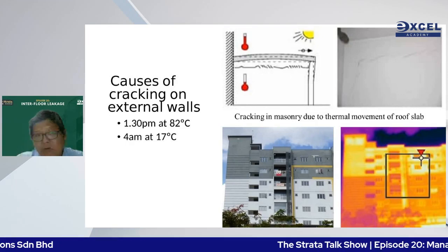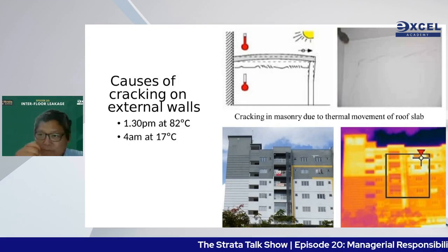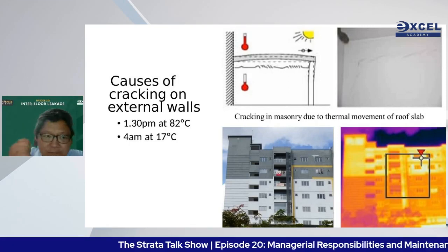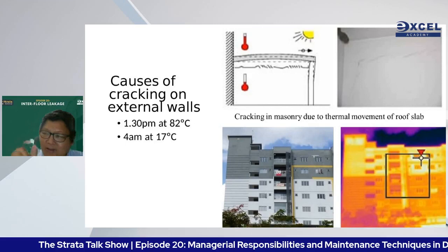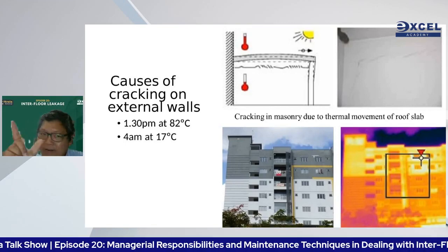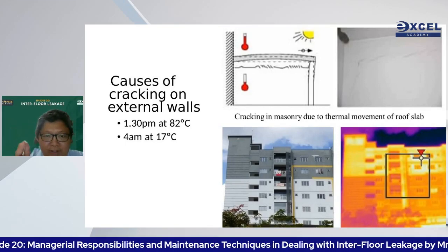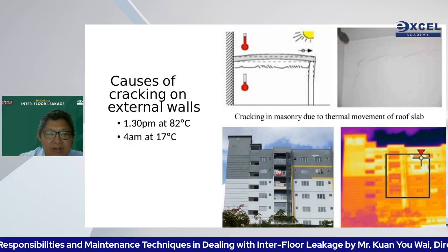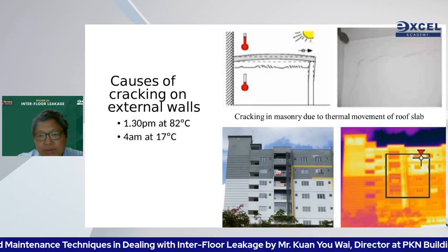And do not try to fill it up with cement, because once you block the area of the movement induced by the heat, it will crack further. You should always use elastic material to seal it up. So next slide, please.